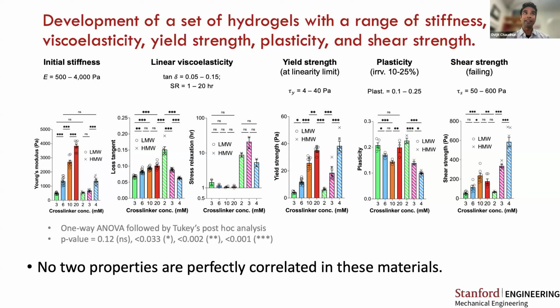But what Byung-Hung did is he formed a set of hydrogels that had a range of stiffness, viscoelasticity, yield strength, plasticity, as well as shear strength. And importantly, no two parameters are perfectly correlated in this set of formulations. So what that means is that these are distinct properties, as we would anticipate, but also if we conduct migration studies in this range of hydrogels, we can potentially relate the migration behaviors to individual properties, as you'll see.